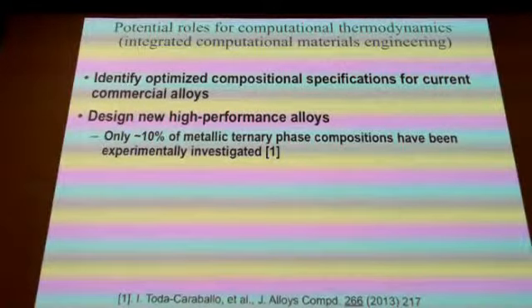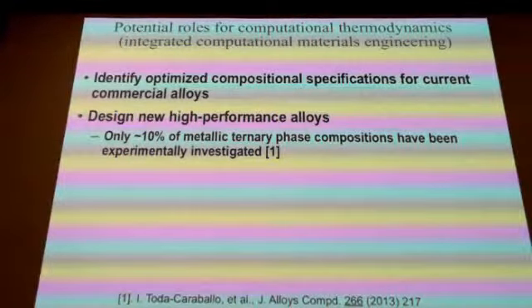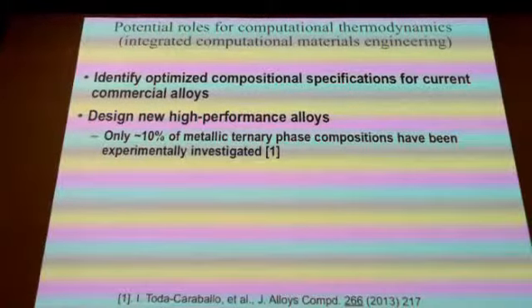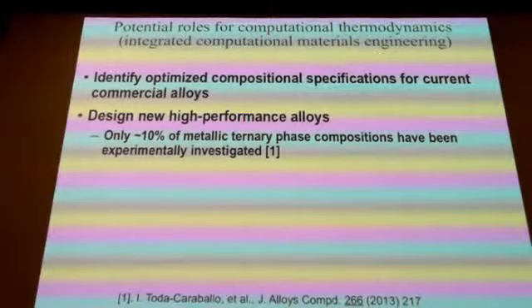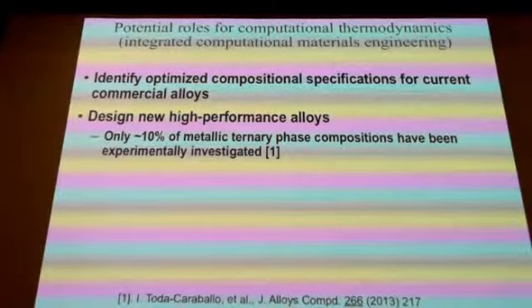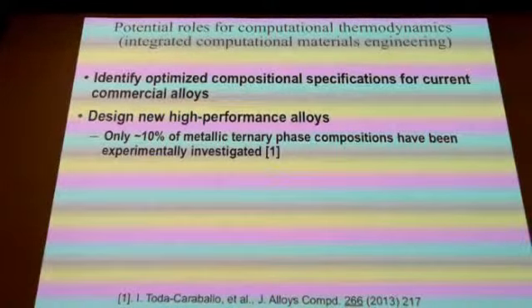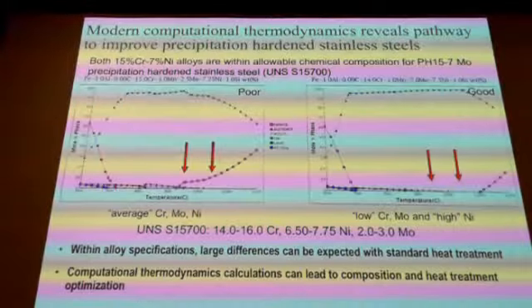And so you would think that after all these decades that all of this has been experimentally studied, and it's actually not even close. So for binary alloys, we've done a reasonable job of exploring the periodic table. But even if you go to ternaries, only about 10% of the possible ternary phase compositions have ever been experimentally investigated. It's 90% we haven't even looked at. And steels are usually made of like 8 compositions. So how many steels have we really sorted out the whole composition?